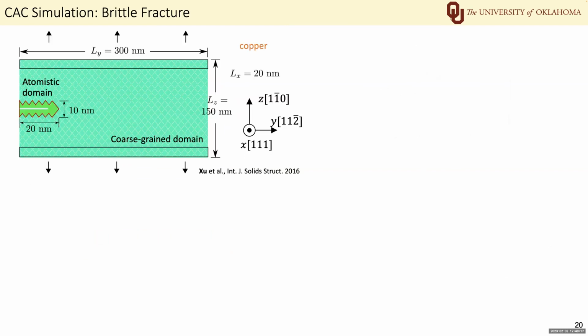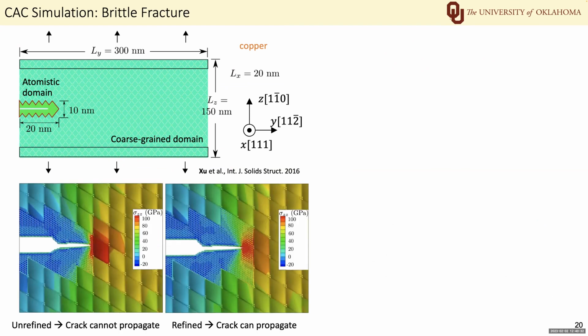So here I show an example in copper. I pull the top and the bottom layer of the system away from each other to simulate the mode 1 fracture. When the finite element in front of the crack tip is not refined, there is a strong stress concentration at the crack tip, and the crack is stuck. Refining the element to atoms would reduce the stress concentration and allow the crack to propagate.